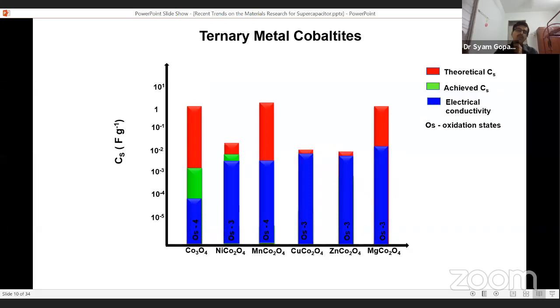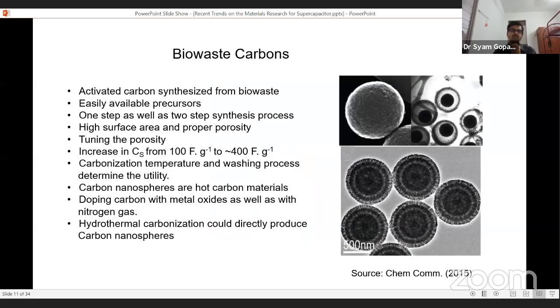Then compared to all these sorts of materials, when we talk about EDLC, the most preferred materials are carbons. So now present researchers are working on the synthesis of bio-waste carbon, and these activated carbons synthesized from bio-waste have the advantage that the precursors are bio-waste, so they are easily available. And the synthesis process is very simple. That means any research lab can synthesize this activated carbon, using a one-step or two-step process.